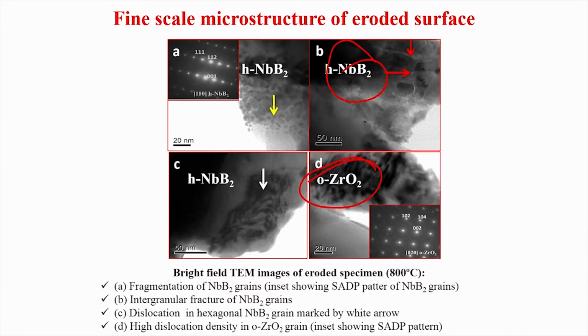Now, as I said, we have seen for the cryogenic sliding wear of zirconia, where tetragonal zirconia goes to orthorhombic zirconia, and before it goes to monoclinic zirconia. When tetragonal zirconia undergoes phase transformations, the orthorhombic zirconia is the intermediate phase. So, orthorhombic zirconia phases are present not only at low temperature sliding conditions, cryogenic sliding conditions, but also when these materials are eroded at high temperature like 800 degree Celsius, again tetragonal zirconia transforms to orthorhombic zirconia.